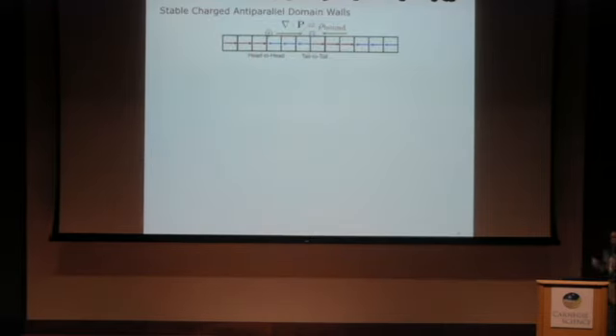I think we decided to look at the charged domain walls in hyperferroelectrics. In yesterday's presentations, we learned that charged domain walls are actually very rare because of this very strong depolarization field. Whenever we have a pair of head-to-head and tail-to-tail domain walls, we have positive polarization bound charge at the head-to-head domain wall and negative polarization bound charge at the tail-to-tail domain wall. This creates a huge depolarization field, which will kill the ferroelectricity.